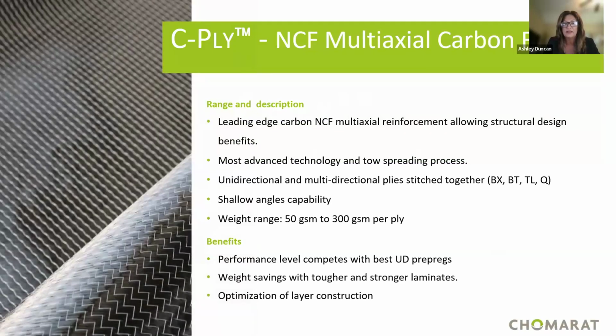So what exactly is C-PLY? C-PLY is our family of multi-axial, non-crimp carbon fabrics. Each ply behaves essentially like a unidirectional layer in terms of performance. Multiple plies can then be assembled and stitched together in optimized orientations to position the fiber exactly where it's needed structurally. Shallow angles can be incorporated, and I'll discuss this in more detail later. And then just the last point is our areal weight ranges from 50 GSM to 300 GSM, that's grams per square meter per ply.